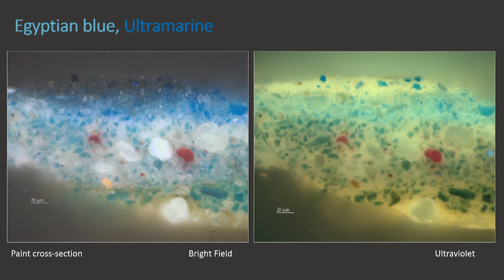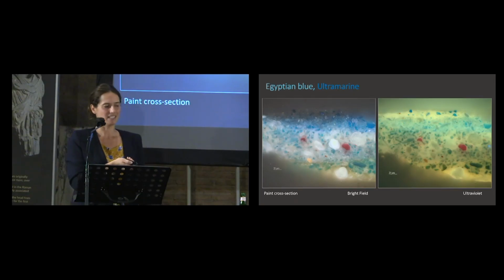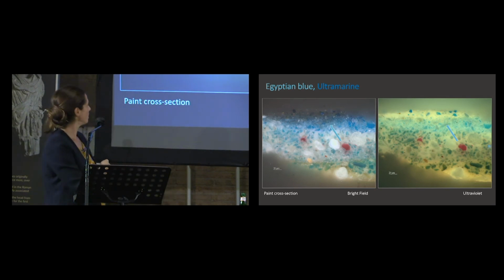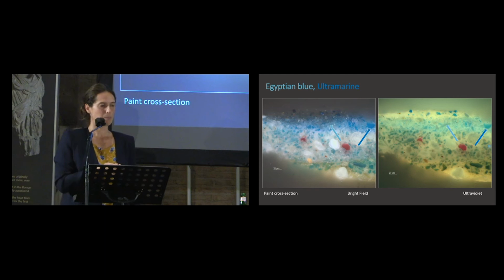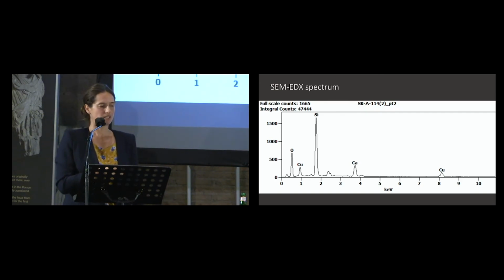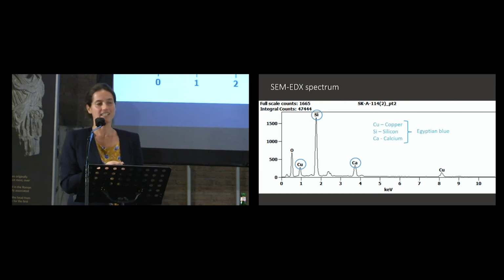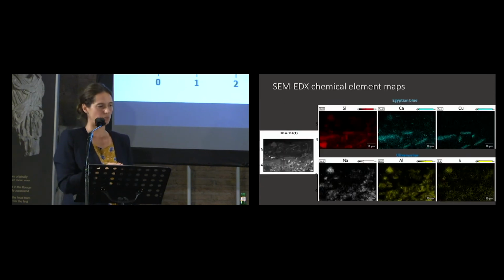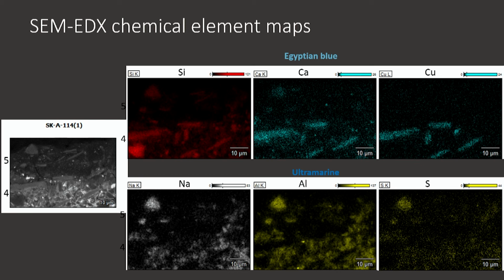And the sample showed that there were at least 4 layers of blue, and Egyptian blue was found in a mixture with ultramarine in the 3rd layer from the bottom, on top of the white imprimitura that you do see here. So the layer containing Egyptian blue is the one up there, and you see the co-presence of 2 different pigments which have different color and shape in the grains. We could, thanks to SEM-EDX, confirm the presence of copper, silica, and calcium in a single grain, and hence confirm the presence of Egyptian blue. And thanks to SEM-EDX, it is also very clear that there are some elements associated with one pigment and some with the other.